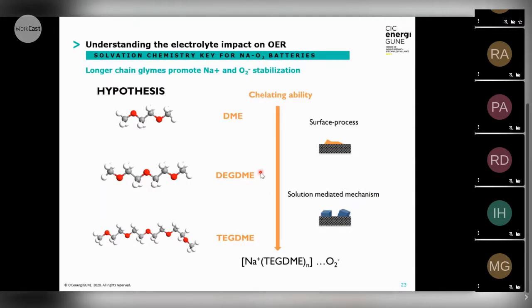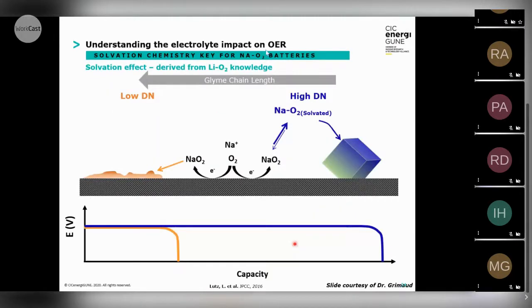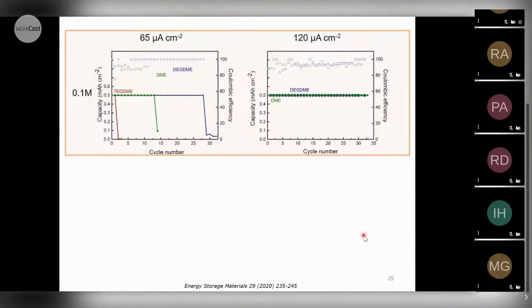So in the case of sodium oxygen batteries, these are the most commonly used solvents, and we wanted to understand the peculiarities of these solvents, because we know that they only differ in the oxygen groups, and as the glyme chain increases, you also increase the chelating ability. So here we can see with the high donor solvent that we have this sodium superoxide solvated in solution, and then it precipitates out of the solution forming these cubes, or you could also have a surface mechanism. That means that the sodium superoxide is formed just on the surface of your air cathode. This gives higher discharge capacity for the higher donor number solvents.